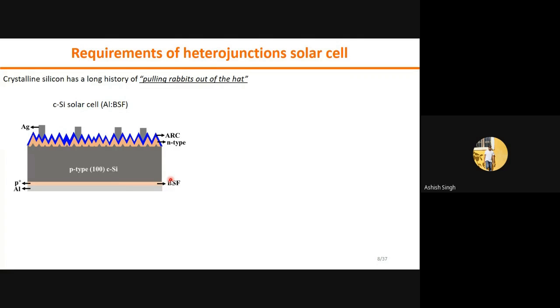Back surface field is nothing but pushing the generated carriers towards the front side. For example, if we shine light on it, an electron-hole pair gets generated, the electron will move in this direction, and the hole will start moving in this direction. That means the electron would also like to move in this direction to recombine with the holes. But if we put the back surface field, it pushes the electrons in the upward direction, and this N-type layer will pull up the electrons. Due to this potential gradient, this solar cell gives good efficiency, and it's already commercialized. But this technology is not free from disadvantages.